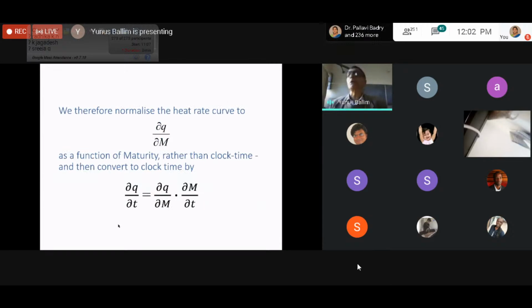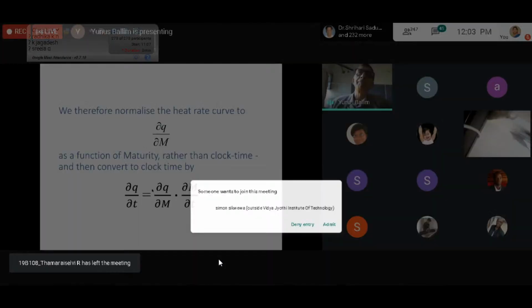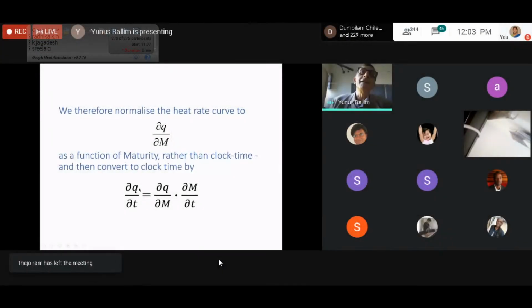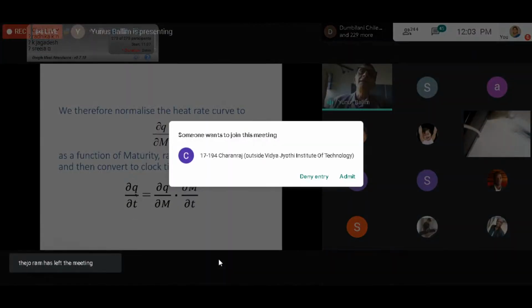And so effectively what we do is we normalize the heat rate curve. Instead of dq by dt, we use dq by dm. M is maturity. The problem, of course, is that the world doesn't move according to imaginary timescales. So you have to find a way back into clock time. And the way you do that is simple, it's through a dot product. You get back to dq by dt by multiplying dq by dm at any time by the rate of change of maturity at that particular time.